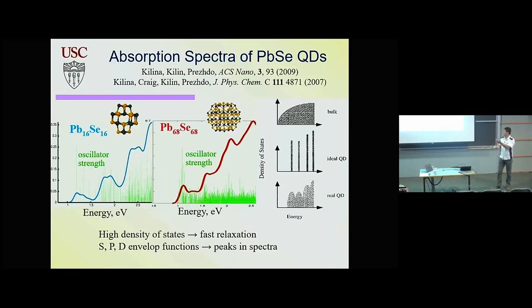And this is something that Eran sees also in his calculations on larger dots. But even in small dots like this one, 100 atoms, you have thousands of states. And if you look at any kind of dynamics, except for very special states right at the bottom, near the band gap edge, you have huge densities of states, and those huge densities of states make your system behave more like bulk than an atom from the point of view of dynamics, because you have many, many states, dark states, that participate in the dynamics.